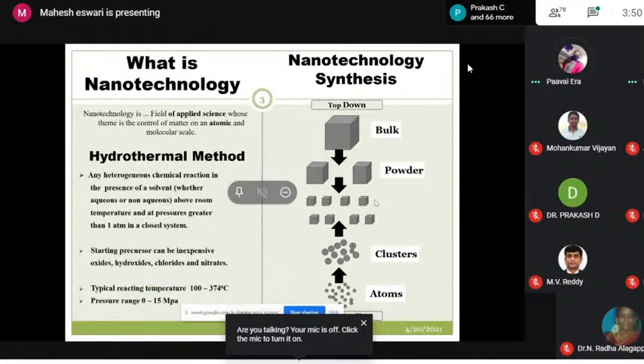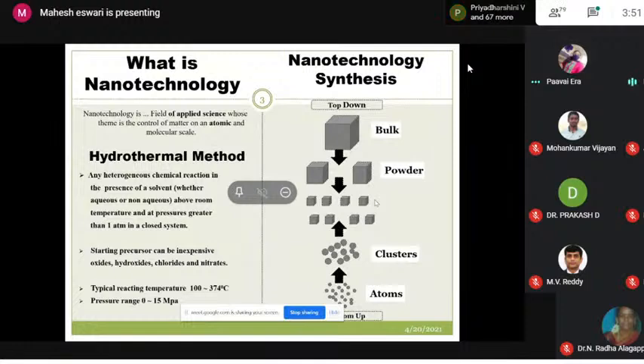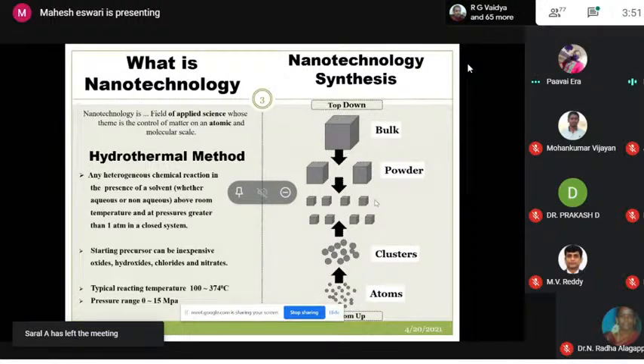We have chosen the bottom-up synthesis, where small atoms combine together to form clusters, and they combine together as nanoparticles. Under this bottom-up synthesis technology, there are several methods: sol-gel, spray pyrolysis, and so many others. We have chosen hydrothermal technology. It's a chemical reaction carried out above room temperature and at a pressure of more than 1 atmosphere. Now, why do we choose this hydrothermal?